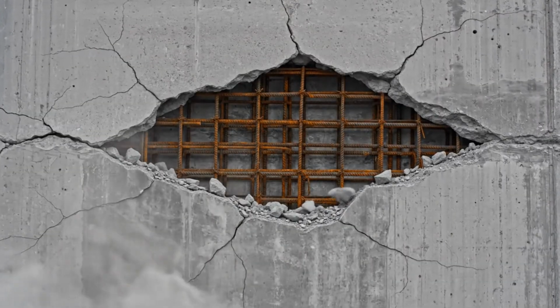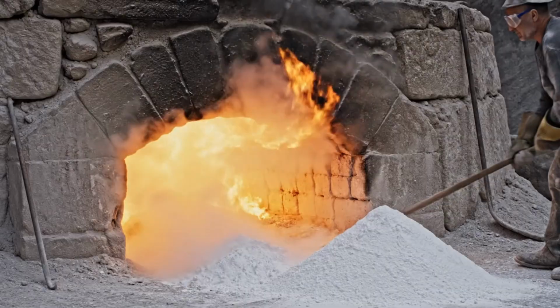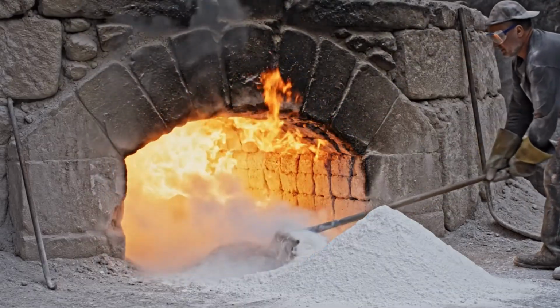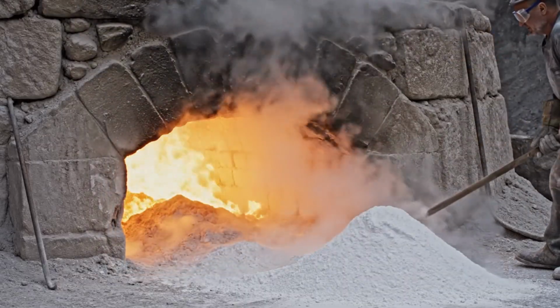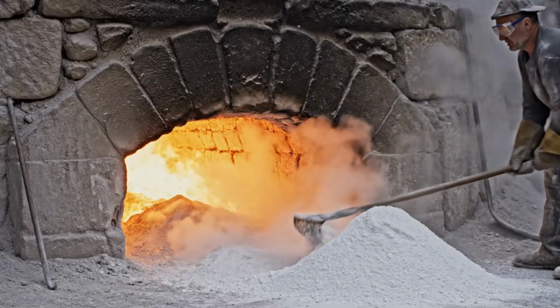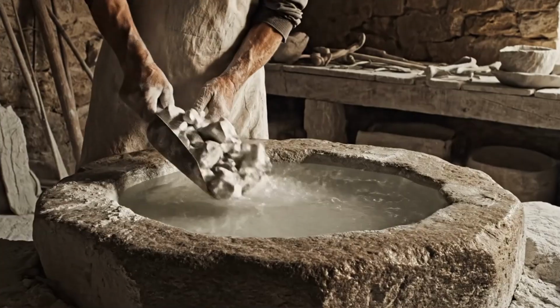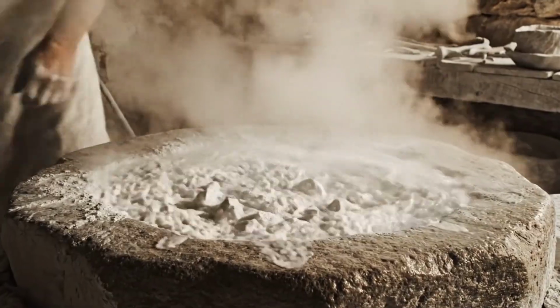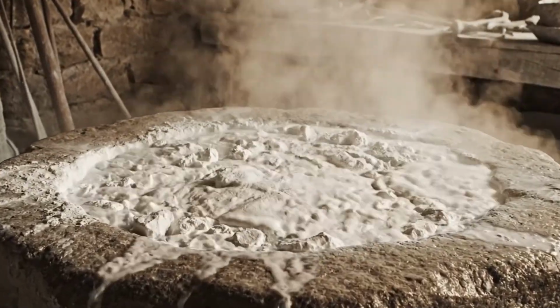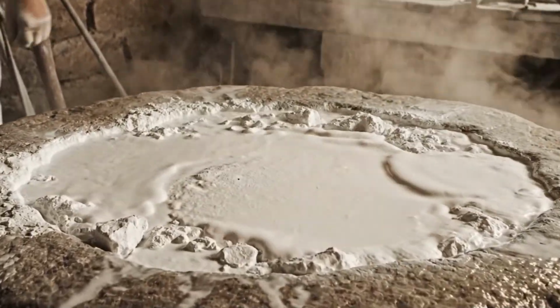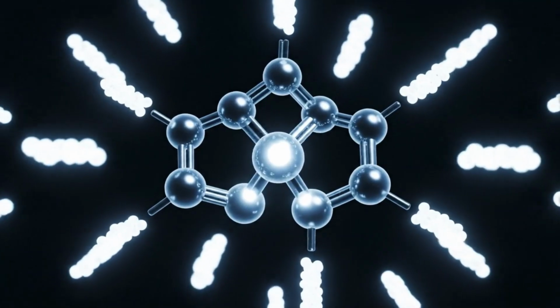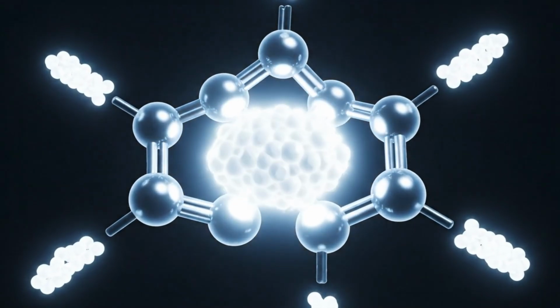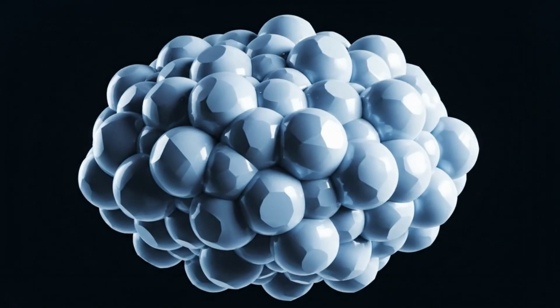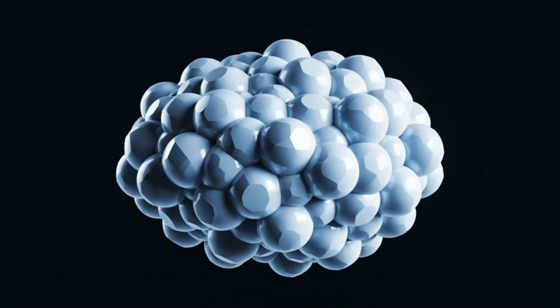If steel reinforcement is present, water reaches the rebar and initiates corrosion. Iron oxides occupy a larger volume than the original steel. The expanding rust generates pressure exceeding the tensile strength of the concrete. The concrete fractures from the inside out. This is spalling. It is the primary failure mechanism in reinforced concrete worldwide. It is not a defect. It is the chemically inevitable consequence of embedding a corrosion-susceptible metal inside a porous, cementitious matrix.